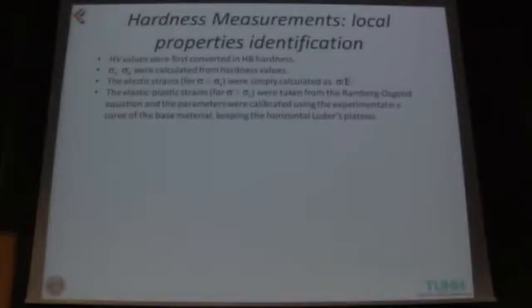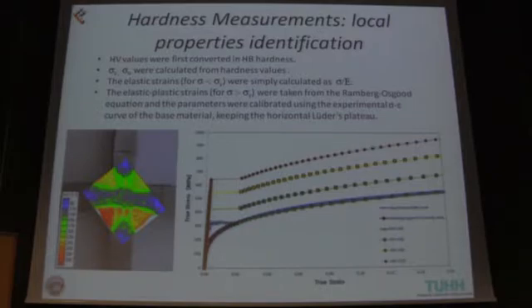So, just to sum up, first of all, we define the different groups of hardness values. Then HV values were converted into HB hardness, and the stress-strain curve was evaluated. The elastic strain was simply calculated as the sigma over E ratio, while the plastic part of the curve was calculated using the Ramberg-Osgood equation. Also the Luder's plateau band was kept, and obviously the base material curve was validated with the hardness measurements.